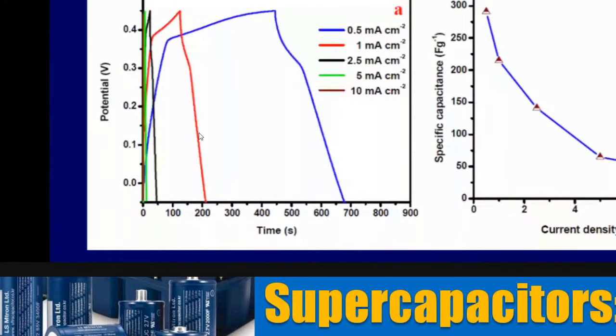You can see that at slow rates, the time taken for charging and time taken for discharge are similar. You can see that up to about 400 seconds you are charging, and the discharging goes up to about 700 seconds. And again, you will see that at half a milliampere, it goes up to 700 seconds, but at higher rates,